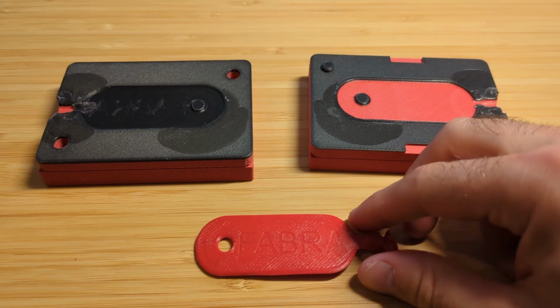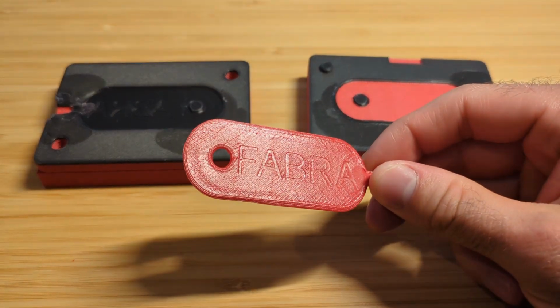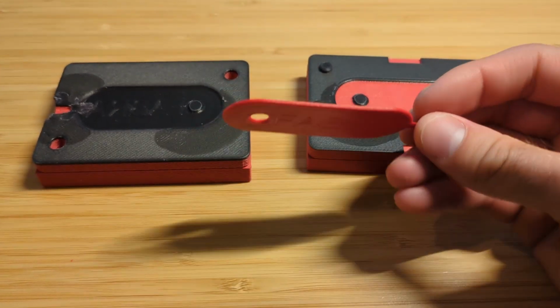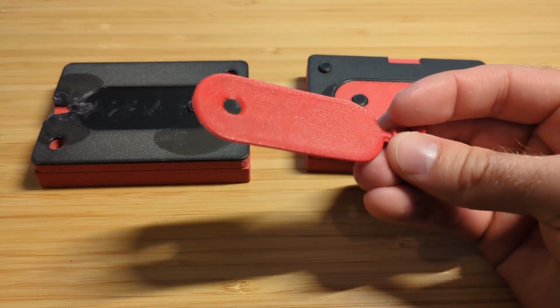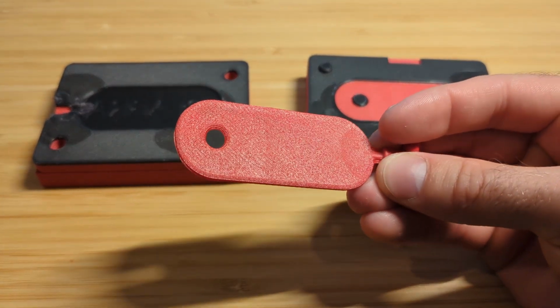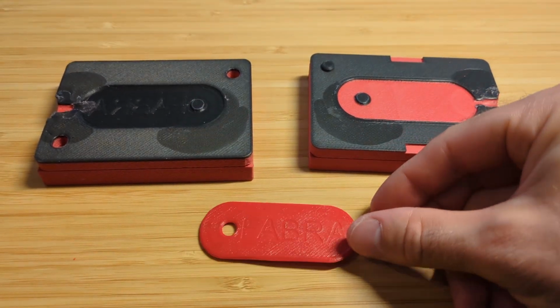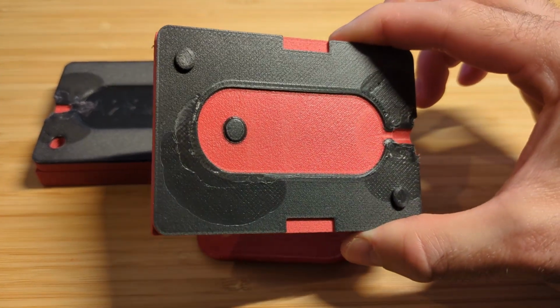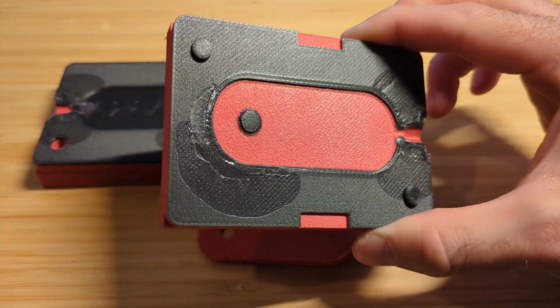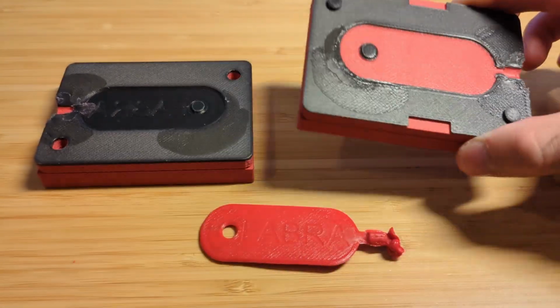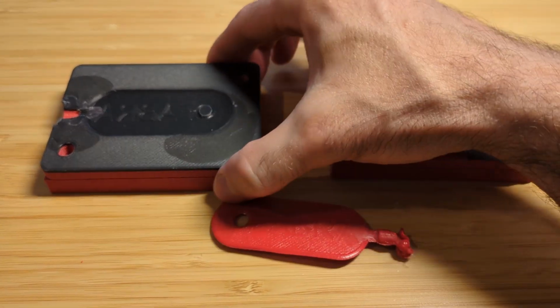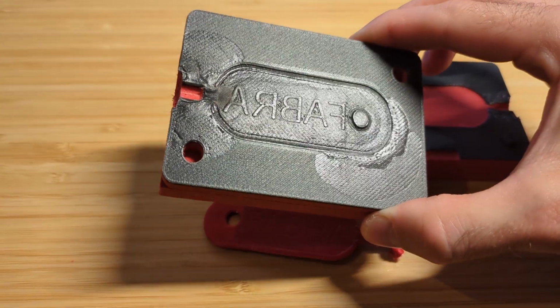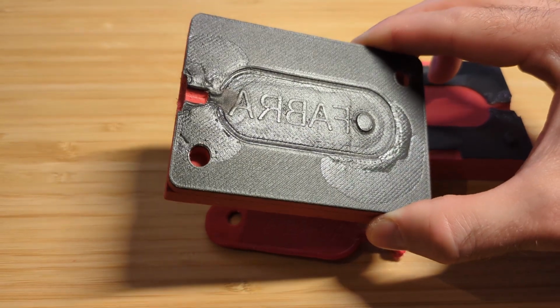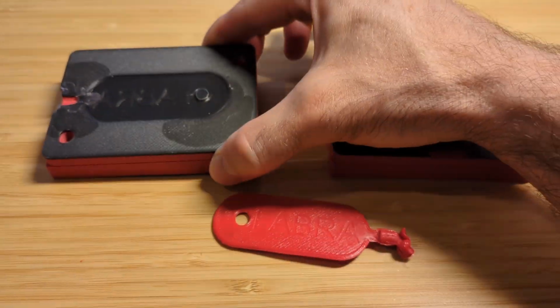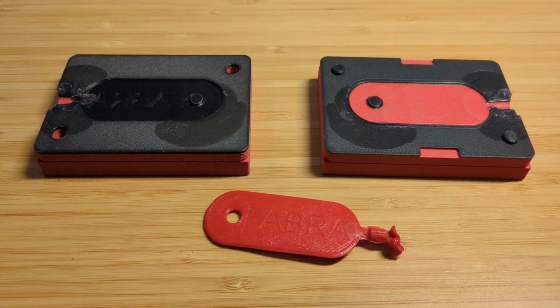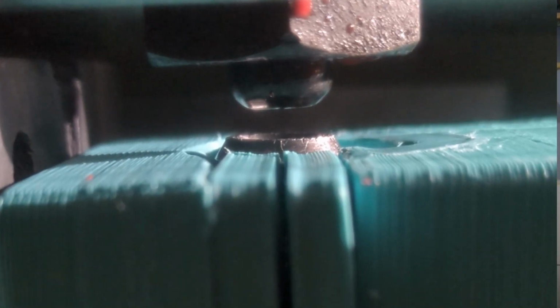The next part, we dropped the wall thickness from 4 millimeters down to 2 millimeters. It reduced the shrinkage and the sink marks that we were seeing on the part. However, we did need to increase the injection pressure to compensate for that. So the black portion of the tool is a standard PLA with carbon fiber reinforcement, so a low heat deflection temperature. The red portion, of course, being the HT-PLA-GF. And you can see here the injection point is quite washed out from the high injection pressures, especially on the PLA-CF.